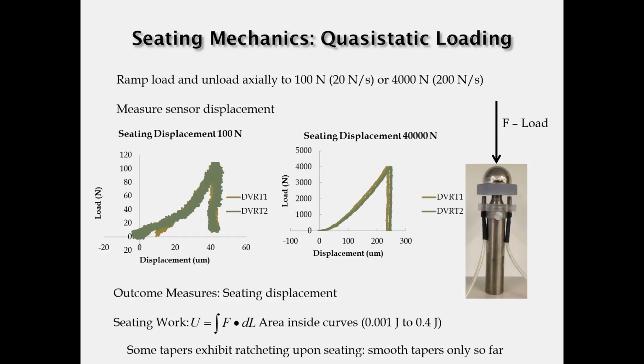In addition, we've recently been investigating how the mechanics of seating may influence the properties and the fretting corrosion reactions at the taper interface. One such test is the seating mechanics test shown here. What we do is we basically apply a sort of quasi-static ramp loading to the head, while also monitoring with two non-contact displacement sensors the relative motion of the head to the neck. And shown are two graphs, one where we're seating only to 100 newtons of load, and another one where we're seating to that should be 4,000, not 40,000, apologies there, 4,000 newtons of load.